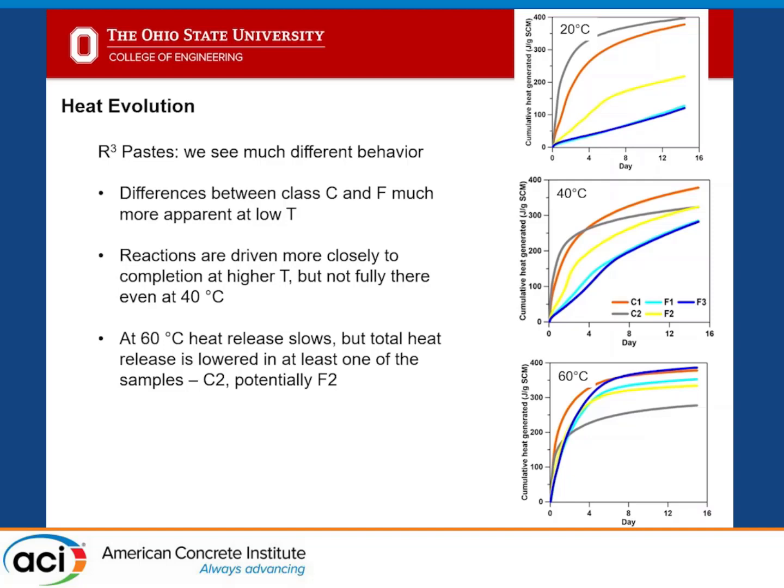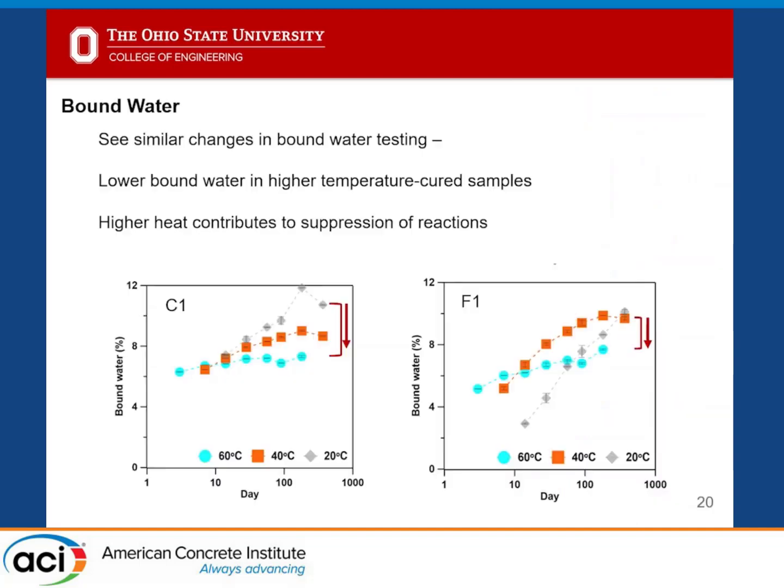It doesn't happen for all of the fly ashes tested here, but we should note that some higher temperature reactivity testing may dull the amount of heat release noticed from certain pozzolans. So if you have that pozzolan, that's problematic, right? But for most of them, we should get relatively okay results at 40C.